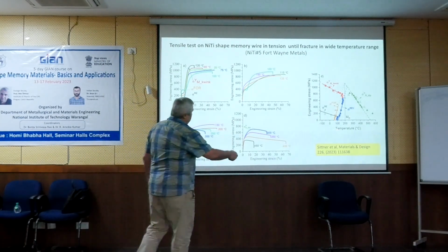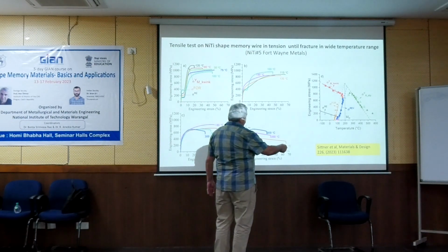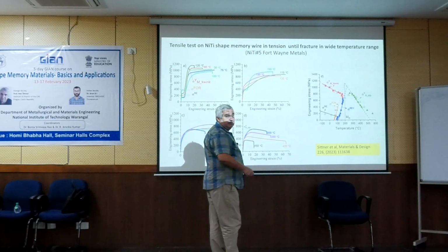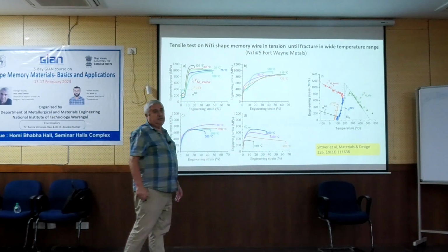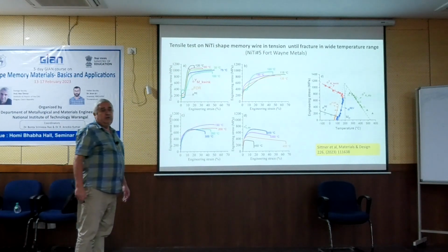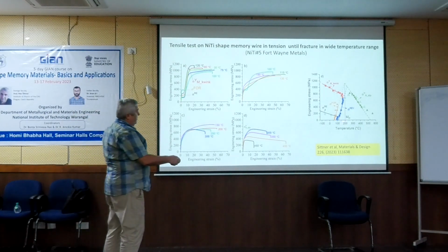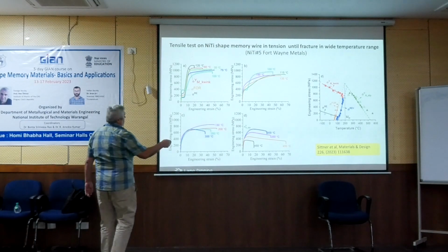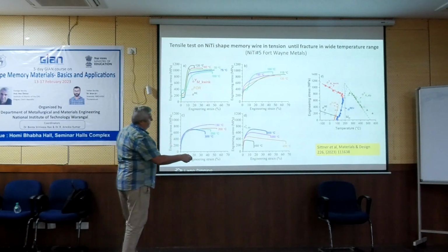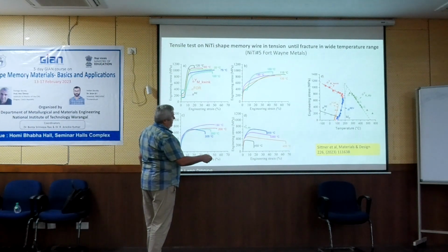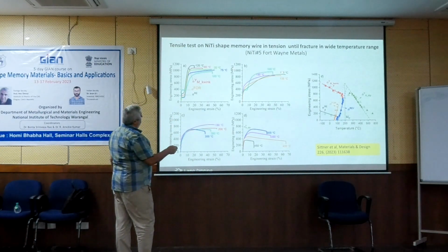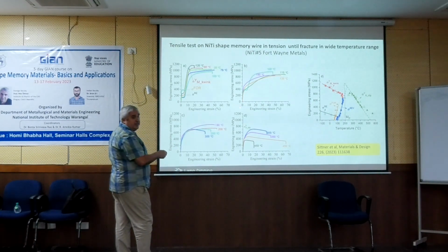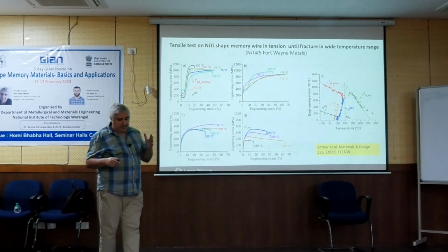The AF temperature here is like 90 degrees, measured from thermal cycling under low constant stress. It's a memory wire. Yeah, okay, at around this curve at 100, it would be superelastic, but slightly more, 115, if you try to make it superelastic, it will end up with some unrecovered strain. It's a good question.